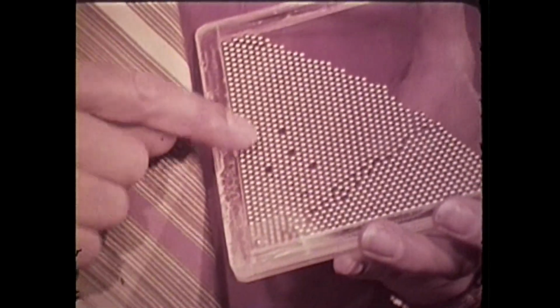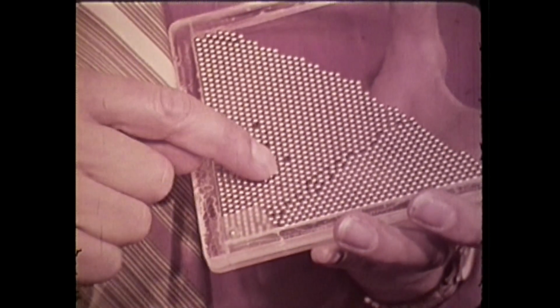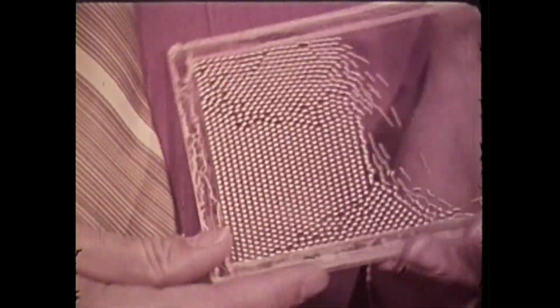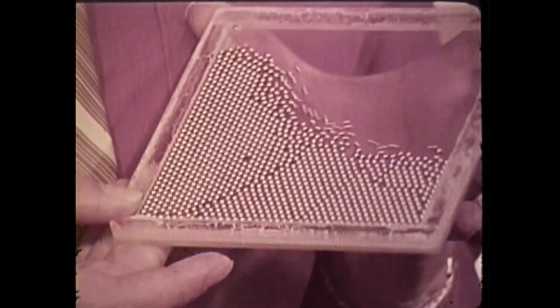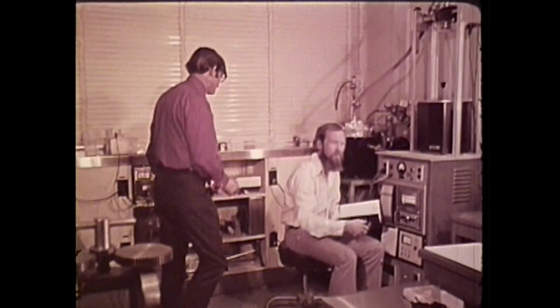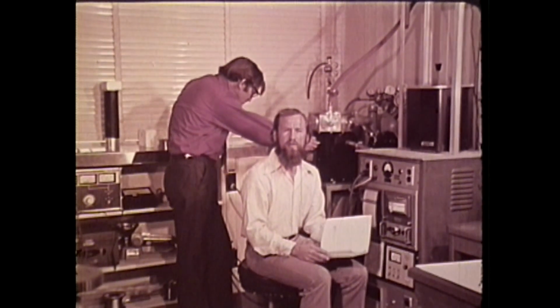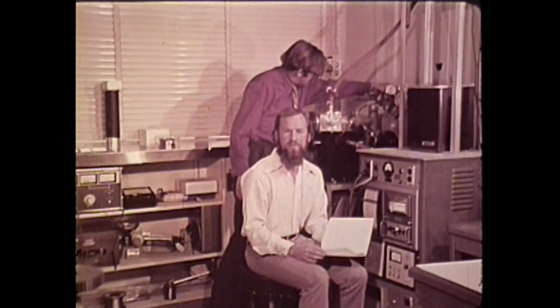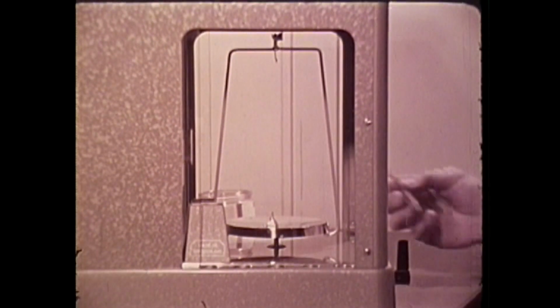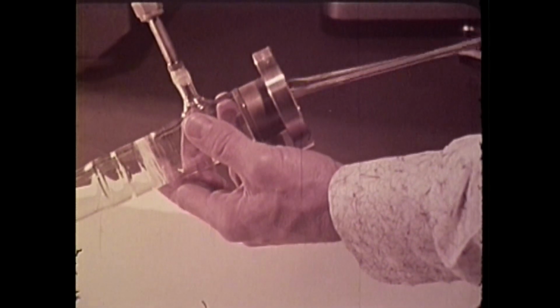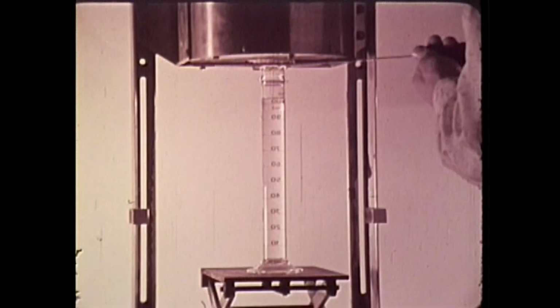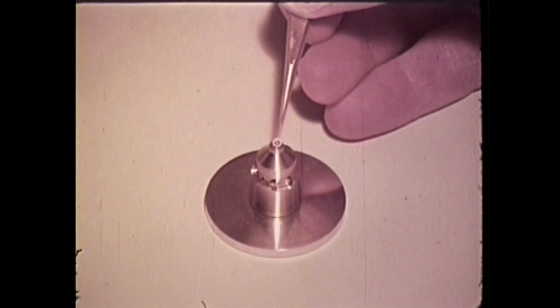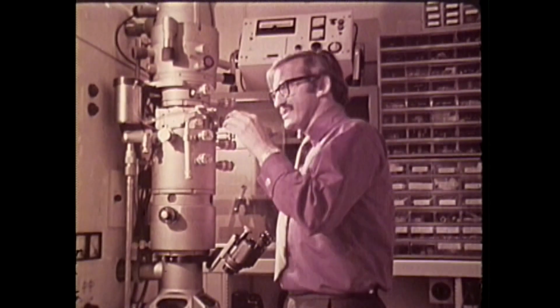We're using the electron microscope to study defects in metals. We are particularly interested in what are known as vacancies, missing atoms in the lattice, because these are known to play an important role in many metallurgical phenomena. For example, precipitation, fatigue, high temperature deformation. One example of our work includes the study of interactions between solute atoms and vacancies in alloy systems. We start our study by preparing high purity samples of simple binary and ternary alloys under controlled conditions. The samples are then rolled to a foil and subjected to a quenching treatment which produces lattice defects. We then chemically thin the specimen to less than a thousandth of a millimeter for direct observation of the vacancy clusters using the electron microscope. We can then monitor the behavior and the size of the clusters during subsequent annealing experiments.